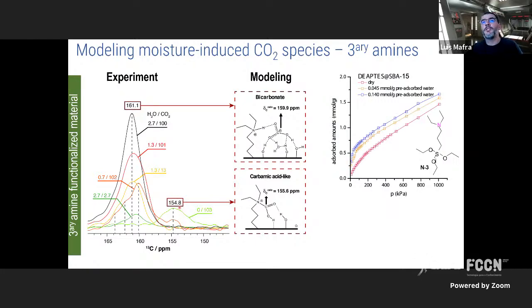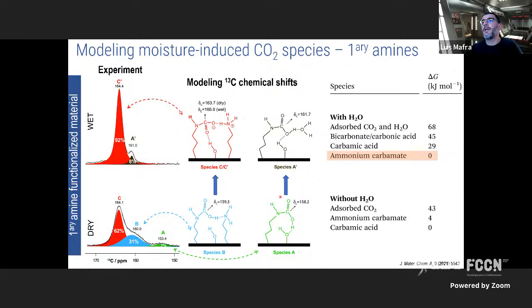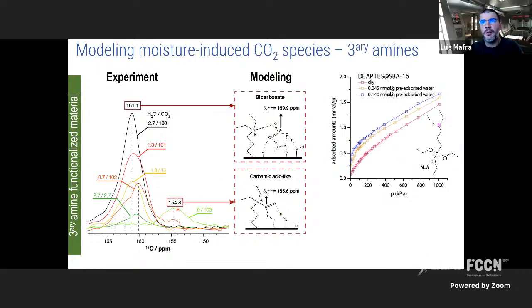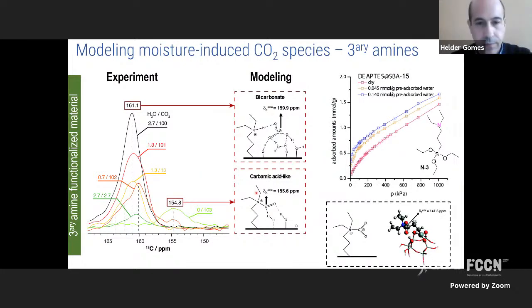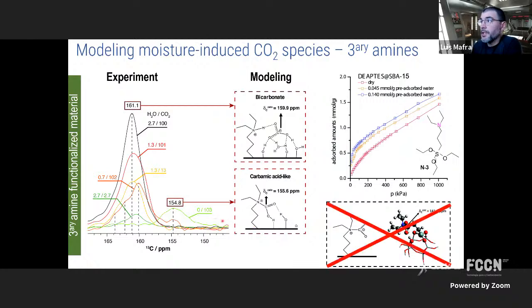We were curious about this peak forming at 155 ppm because we cannot form any carbonic acid. We assigned previously this 150-something ppm peak to an isolated carbonic acid. And we see it again, but in a tertiary amine. And it appears that we can form, in fact, a carbamic acid, which was never claimed before. But we could also form a zwitterionic species, okay? But the chemical shift is much lower than this one, so we can just discard it.